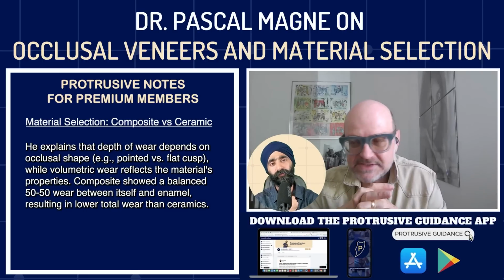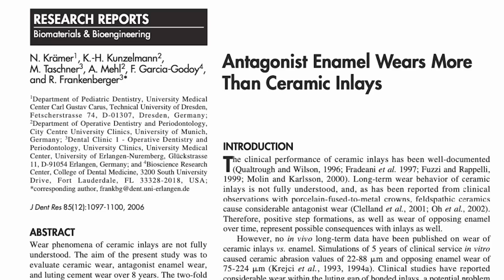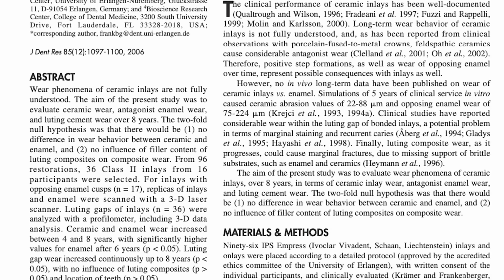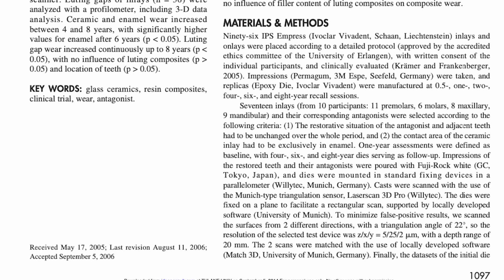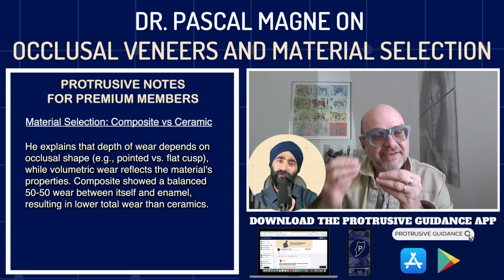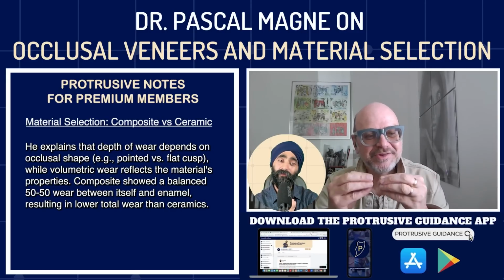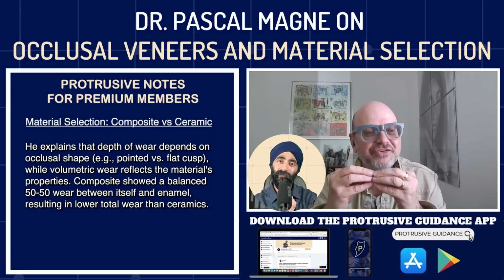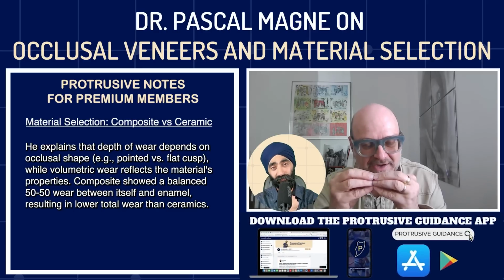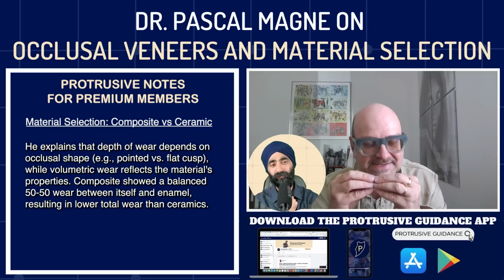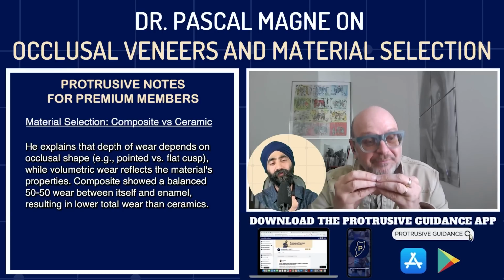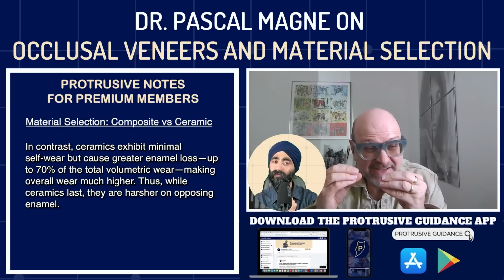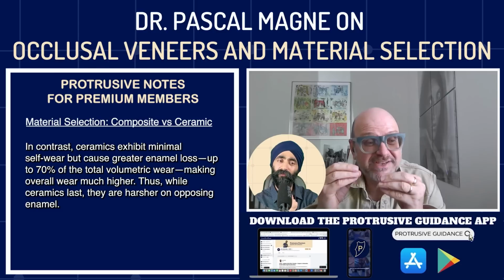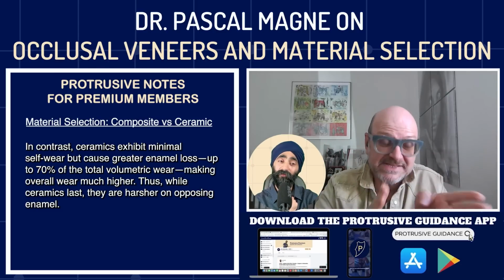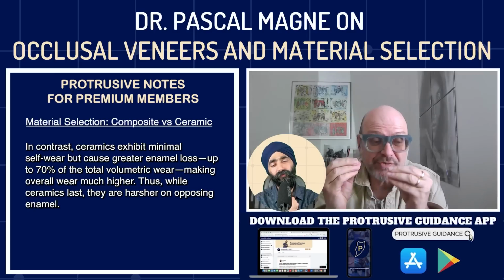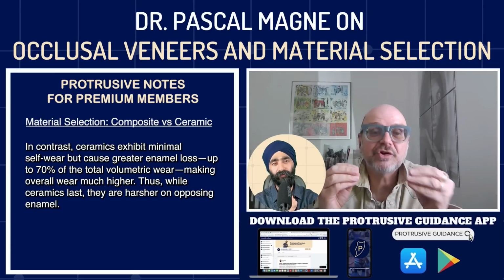But what is characterizing a material is the volumetric wear. So when you look at this study, and there's an excellent study by Kunzelmann in Germany, they look at enamel wear against different materials, but they look at the volumetric wear, and suddenly you see that enamel against composite, it's 50-50. You will see 50% on one side, 50% on the other side. And the total wear, the additive wear of those two volumes, is always going to be less than with ceramics. So with ceramics, the ceramic itself will wear very little, maybe only 30% of the total wear, but the 70% or more will be the wear of the antagonistic enamel. But the fact is that this 100% of volume loss will be much bigger than with composites.